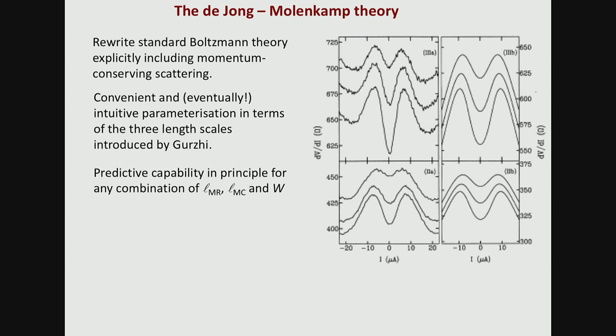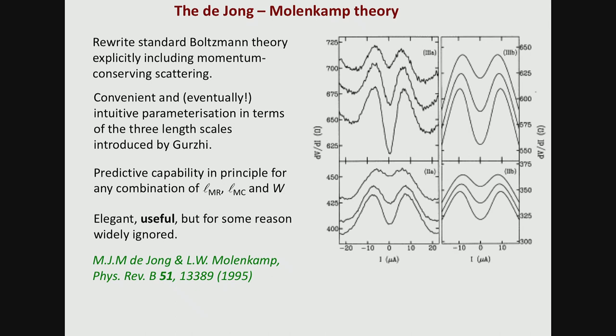And what they did, which was very appealing to us, was they did a development of Boltzmann theory to go beyond the standard, which is called the relaxation time approximation, and they then included higher order terms in the analysis, which gave them sensitivity to be able to analyze hydrodynamic effects if they had them. And within that theory, they were able to publish pretty satisfactory qualitative agreement between the theory they were doing and the data they were taking.